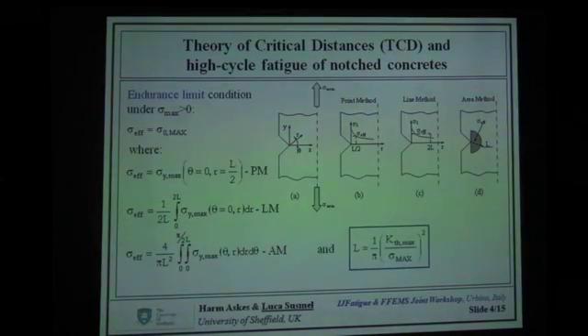The common feature of these three formalizations of the same idea is that L is a material property which can be calculated by using a linear elastic fracture mechanics property, the threshold value of the stress intensity factor, and a continuum mechanics property, which is the plain material fatigue limit. But when it comes to concretes, the problem is that it's very difficult to determine the threshold value of the stress intensity factor, simply because they are super brittle. So we need then a trick to be able to estimate L, even if we cannot determine the threshold value of the stress intensity factor.